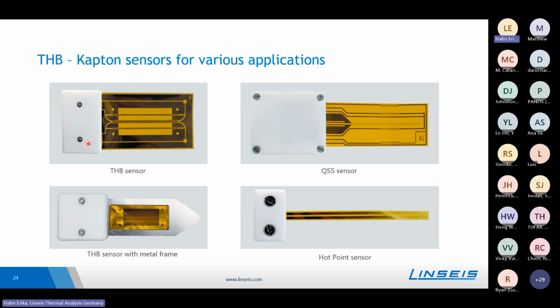The first sensors which were available with the instrument are the so-called THB sensors. This is also where the instrument got its name from. These are for quite low conductive materials and can also be used for liquids and powders. But in such a case, we have the metal frame on top because this sensor is very flexible, and for liquids, it's better to have a stable and stiff sensor. For the high thermal conductivities, we use the QSS sensor. QSS stands for quasi-steady state sensor, so here the measurement time will be a little bit longer, as we wait until almost a steady state is reached.